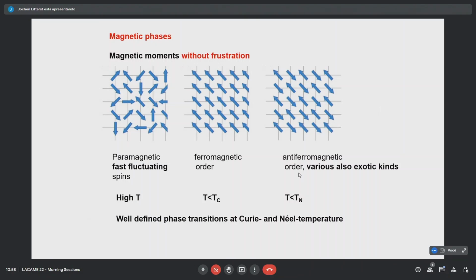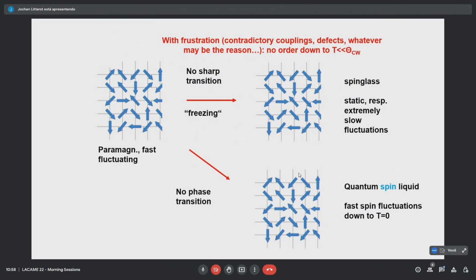What happens if we now introduce frustration? That can come from contradictory information from nearest neighbor couplings, for instance, or from defects. It may occur that we do not have very well-defined transitions. At least nothing will happen if we pass the typical temperature which corresponds to magnetic interactions, like the Curie-Weiss temperature. And then the spins which are fluctuating fast at high temperature will slow down, and they may freeze to a spin glassy state. Ideally it will be statically frozen, but usually there's some relic of slow fluctuations.